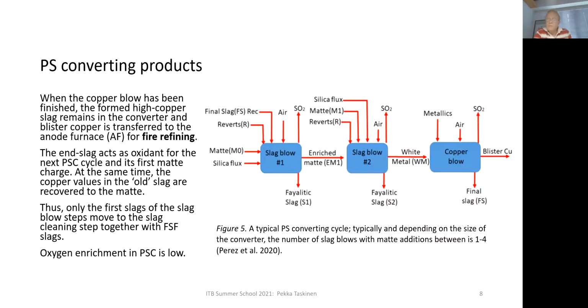And because we are not producing slag here anymore, there must not be any elements which are oxidized in the copper blow stage. The resulting material is called blister copper. So we have final slag here, which often remains in the converter, waiting for the next furnace matte ladle and charge. And this blister copper is poured to the anode furnace.